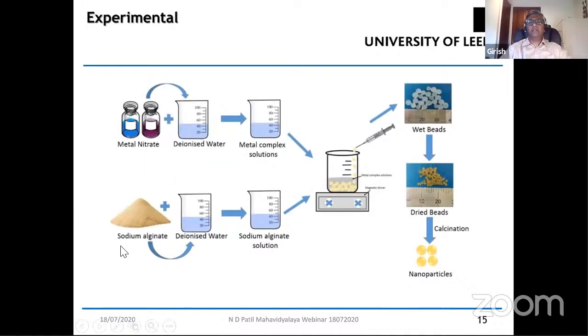So what we have done is, this is a simple schematic diagram. We have the metal nitrates or metal salts that are mixed in appropriate ratios to form the compound. And then you have the sodium alginate, which is converted in the form of gel. So the powder is converted into gel. And once you bring the alginate in contact with metal ions in the solution, it instantaneously converts into beads, and these beads are then dried and calcined to produce nanoparticles. This is a very simple schematic diagram of how we produce nanoparticles.